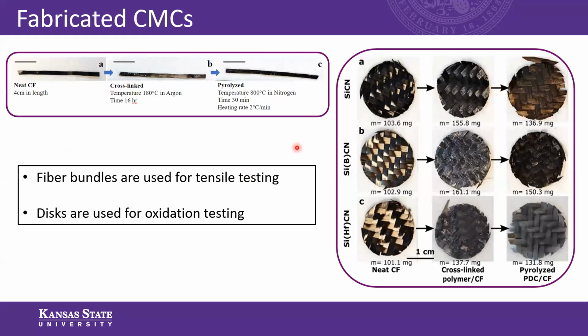And here are the fabricated CMC images. So fiber bundles up here are shown. These were used for mechanical testing in the form of tensile testing. As you can see, here's the progression between neat or uncoated, cross-linked, and pyrolyzed. And then these discs were used for oxidation testing. So similarly, we have neat or uncoated, cross-linked, and then the final pyrolyzed mini CMC.